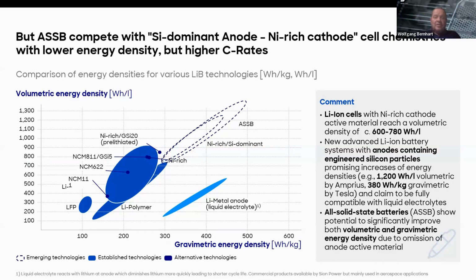So if we compare all solid state batteries, we need to look at the volumetric and the gravimetric energy density. As you can see here with the dotted lines, all solid state is better than what we have today with NMC, even with NMC with graphite and, for example, 5% silicon. But the issue is it's also not necessarily much better than nickel-rich chemistries with a silicon-dominant anode and potentially a liquid electrolyte.